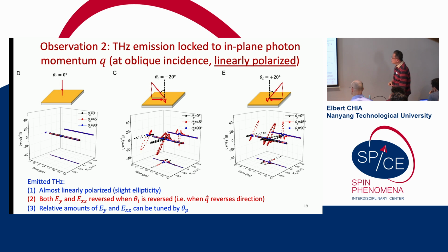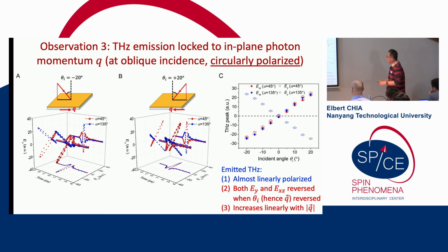Now, what if we use circularly polarized light? We see the same thing. You can see here that there's a flip from negative to positive, and there's a flip from negative to positive. So the conclusions are the same. And once again, when we change the incident angle, we also change the magnitude of Q, and so it's consistent with photon drag once again.